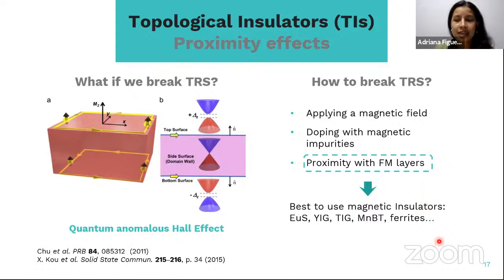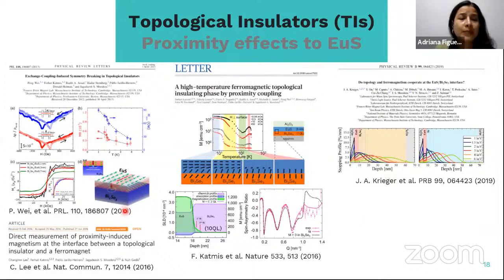And in this case, as I said, it is best to use a magnetic insulator in order to avoid the interference between those surface states and the metallic character of the magnetic material. So here, for example, I'm showing some materials that you can use. You can use europium sulfide or rare earth garnets or other novel materials that are being explored, like ferrites or these materials of bismuth telluride or antimony telluride using transition metals like manganese. So I'm going to show you some results about what we've done to study proximity effects of the TIs with europium sulfide.